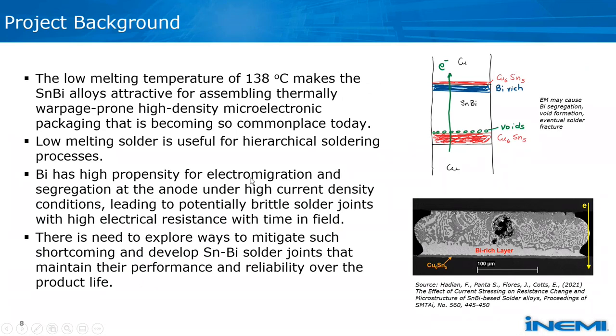So some background information. We find that we have tin bismuth as a very attractive low melting alloy, and iNEMI has done a lot of mechanical studies showing the advantages of using tin bismuth alloys for low temperature solders. So one reason we like to use low temperature solders is because of warpage of high-density microelectronic packaging that is becoming so commonplace. Also, if you're doing hierarchical soldering, which means you have many soldering steps, the later soldering steps should not melt the earlier solder joints. So that's where the tin bismuth would come in handy. This would be probably the last solder joint you make with the tin bismuth solder.